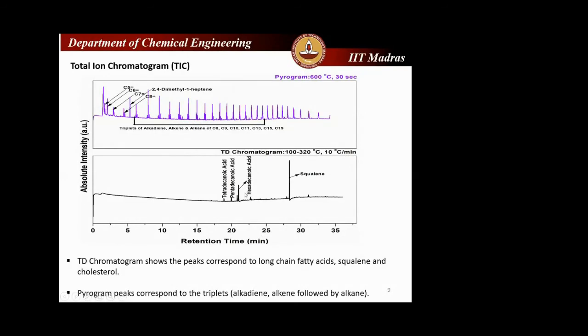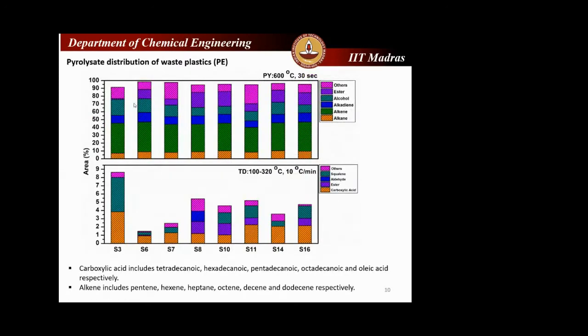As you can see, I got all these compounds in the thermal digestion range, and after that I subjected the same sample to pyrolysis, which was carried out at 600 degrees centigrade for up to 30 seconds. I got all these for the polyethylene sample. If you pyrolyze polyethylene, you will get the triplets in the chromatogram, which are alkadiene, alkene, and alkane, followed by low molecular weight olefins with a double bond, like pentene, hexene, heptene, and octene. So this is the overall distribution I got for the waste plastic, like polyethylene.